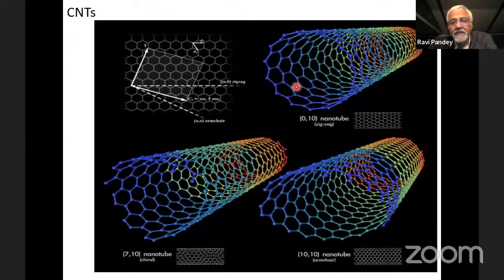So this again is the cartoon of the carbon nanotube, and most of us know that, if we take the plane of the paper, depending on how we roll the paper, we can have the zigzag type of carbon nanotube or an armchair carbon nanotube, and in between we have the chiral carbon nanotube. And interestingly, depending on the way we fold these nanotubes, it can be either metallic or semiconducting. So that's the difference depending on the direction.